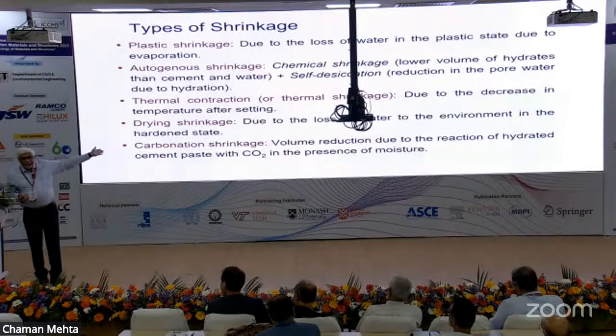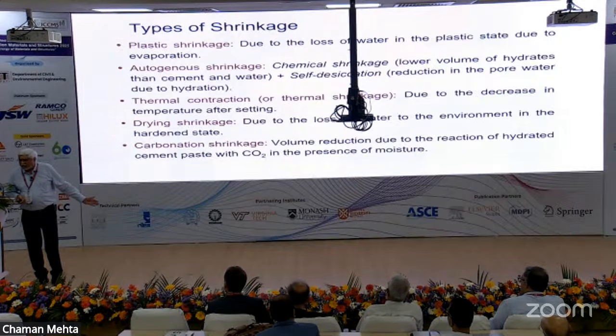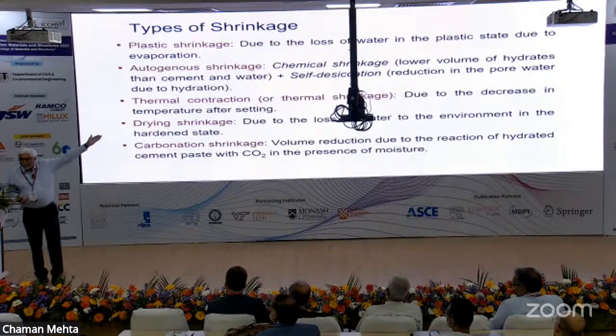So the first 3, we never studied about. When I was a student, we never studied about the first 3. Because you had so much water in your concrete, it did not crack due to the first 3. Drying shrinkage was important. Now you're putting so little water, you're putting 0.3 water cement ratio, 0.25 water cement ratio. The first 3 are becoming important. Drying shrinkage and carbonation, maybe not.